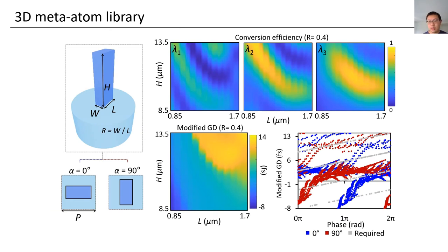Okay, with this big advantage of the 3D meta-atom in mind, the next step is to build up the 3D meta-atom library and find the correct structures to simultaneously offer the phase and the group delay response. So we consider 3D meta-atom structures like this with different heights, widths, and lengths, and we define the aspect ratio R equals W divided by L. We set up the meta-atom to have only two possible orientations, either 0 degree or 90 degree, which removes the polarization sensitivity. Because we know the output of the single mode fiber has random polarization, in order to maximize the benefit of this lens, we have to make it polarization insensitive.